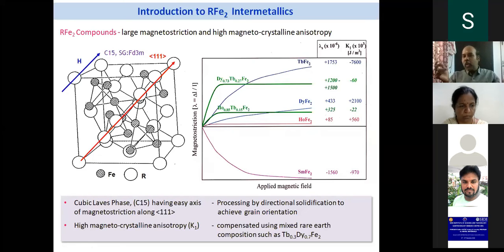So there is a requirement to reduce anisotropy. That means that it is saturating at high magnetic field essentially signifies the magnetic anisotropy in this material is high. So to reduce the anisotropy, something called anisotropy compensation was carried out. Anisotropy compensation was carried out by mixing two different materials having different anisotropy constants, and such a material is called